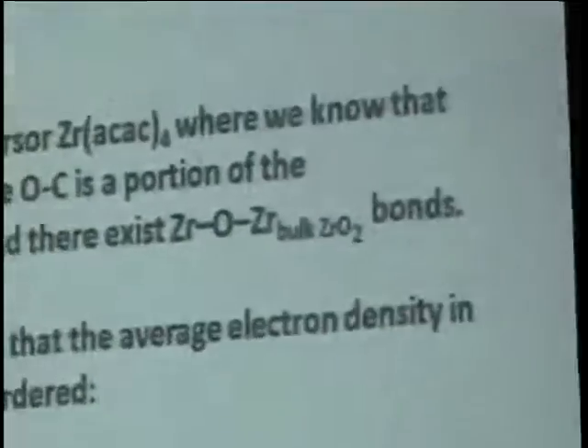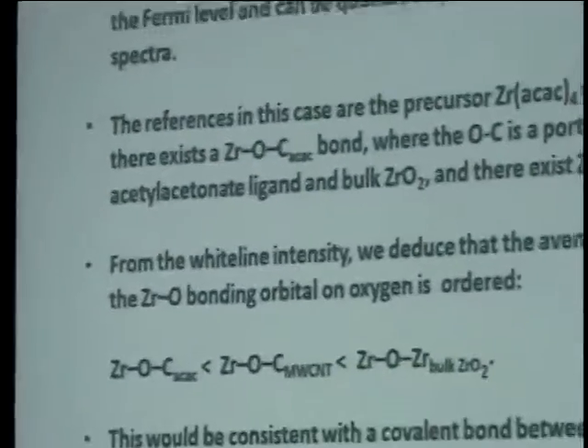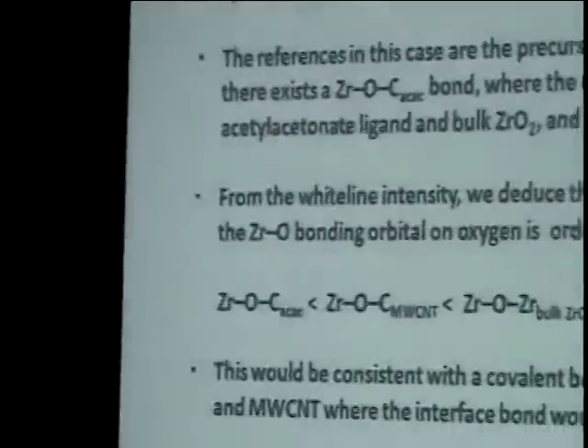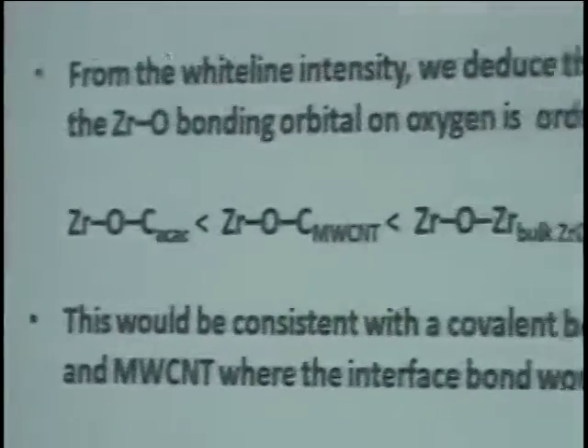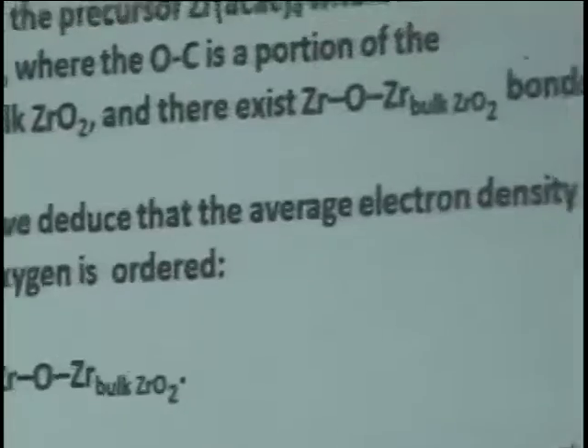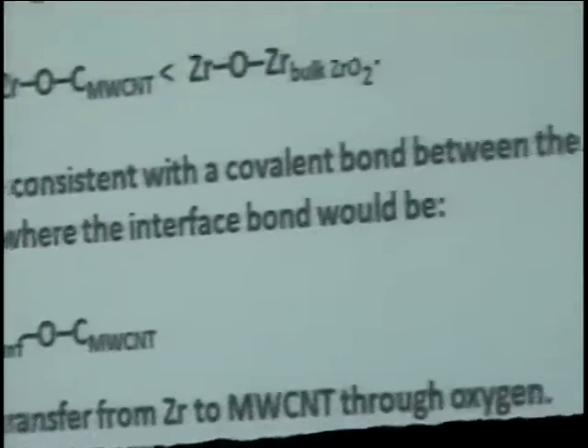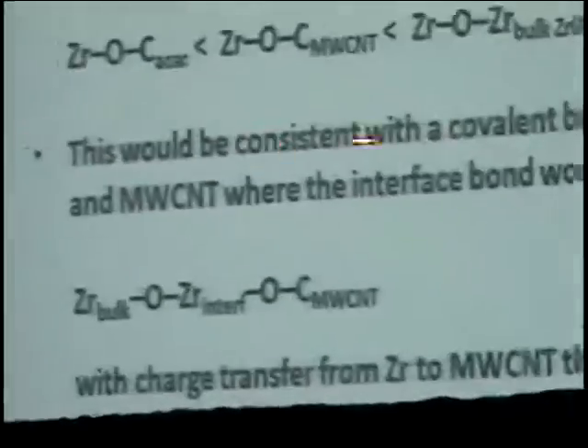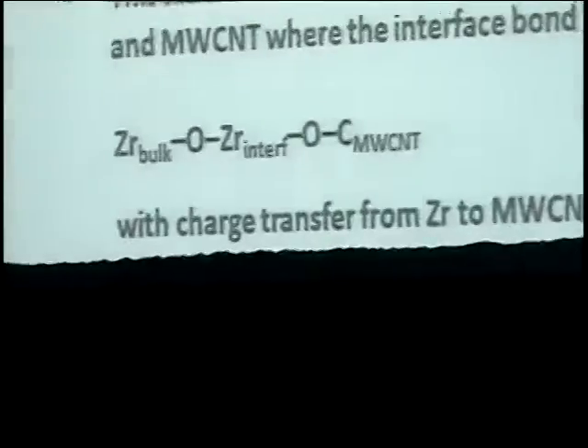And so if you have more empty states, you get higher intensity, as you do with the precursor, the acetylacetonate. If you get a lower intensity, that means there's more electron density and fewer holes near the Fermi level. And our catalyst falls right between the precursor and bulk zirconium oxide. So all I can do is a qualitative discussion about which way electrons go. In this case, it's with respect to the bulk.